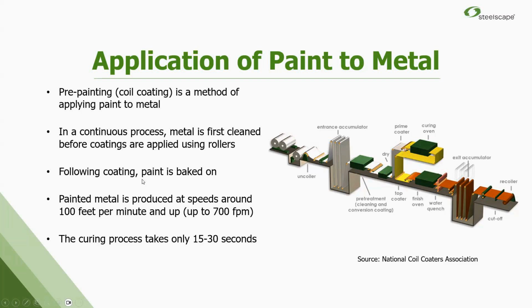It's all solvent-based, baked on. So we are applying paint, drying it, curing it, and rewrapping that coil, usually in like 15 to 30 seconds. So it's very, very fast. All of these paint lines vary a little bit in configuration and capability, but this is kind of a generic layout here. These lines run anywhere from 100 feet per minute up to 700 feet per minute. So like I said, very, very quick.